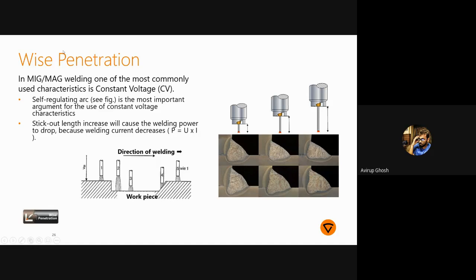But when we have this particular software switched on, this software basically detects if your current is dropping during welding. So if you have a movement of the torch like this, or a movement of the job like this itself, we can take around 25 mm of variation from the torch path. So if your torch path is around 15 mm, and you are moving away to around 35 or 40 mm, we can take the variation. But you have to keep in mind there's another factor in this path movement, that is gas. When you move away, you need a higher gas input to keep the porosity out. Otherwise, there's a high chance that you will get much more porosity in these 30 mm or 35 mm stick out length jobs.